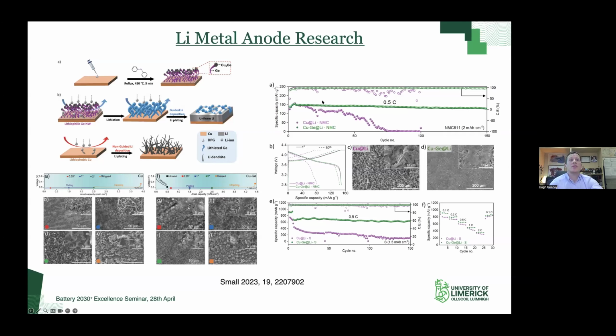So comparing different chemistries, we have our standard copper as the control here. These were just plated with the same amount of lithium in each case. So in the purple case and in the green case, the only variable is the inclusion of that thin layer of lithophilic germanium. What you can see is, with an NMC 811 cathode chemistry up to 2 milliamp hour per centimeter squared capacity, we have much better capacity retention in the case of the germanium-containing anodes. And for the lithium sulfur chemistry down here at the bottom, again, it degrades much more rapidly in the absence of the germanium. We were primarily linking this to anode changes because the cathodes were fixed in each case.